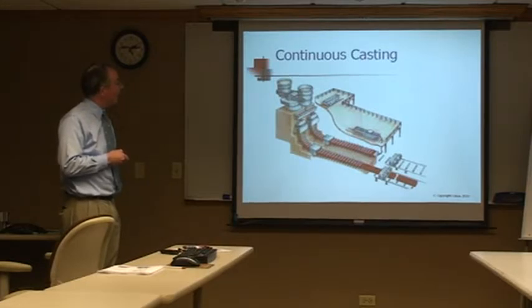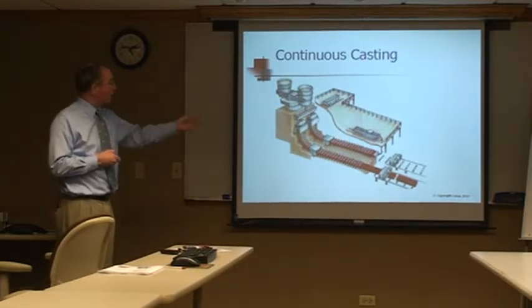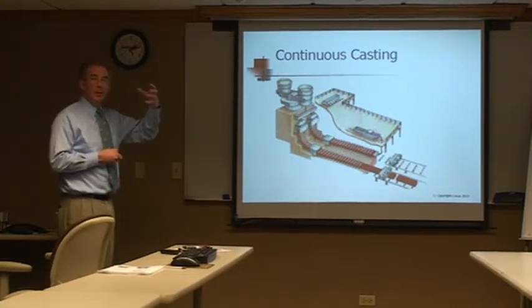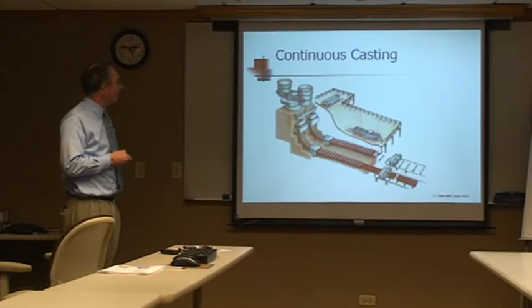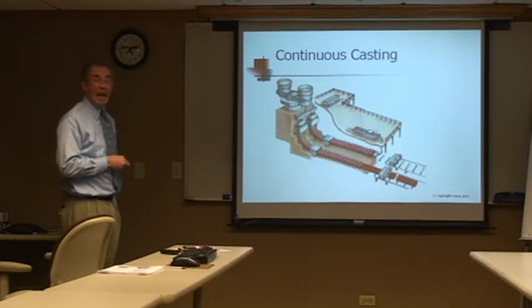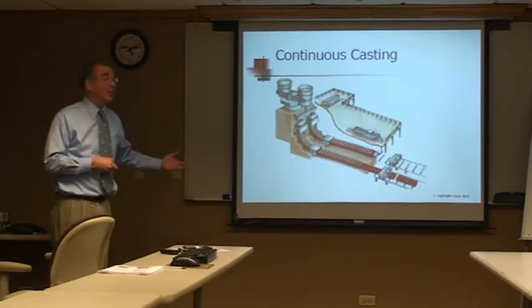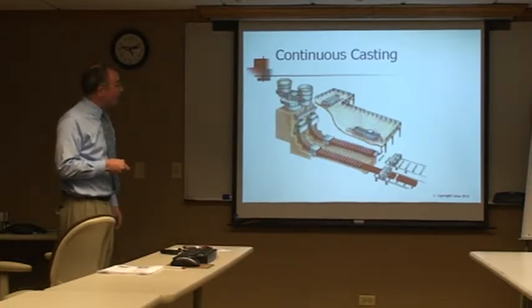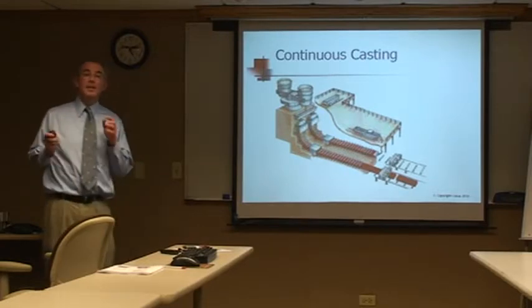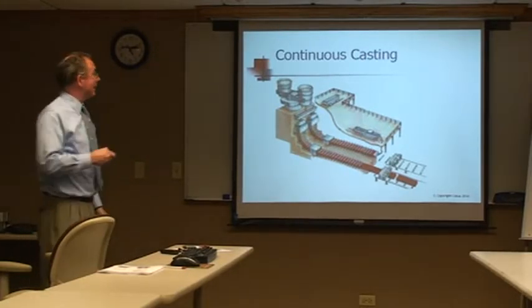And then at the bottom of the tundish are molds. They're copper-cooled molds, and we'll see a cross-section here in a second. That chills the steel into a shell. As it pours through into these molds and comes through, there's water spraying, and these rollers extract the solidifying steel, so that as it's coming out, the shell is solidified, and by the time it gets to here, it's just about solidified. Then it becomes an as-cast slab. It could be a bar, a round, or a square. As it comes down here, there's a series of torches, and it just cuts the section off one at a time.